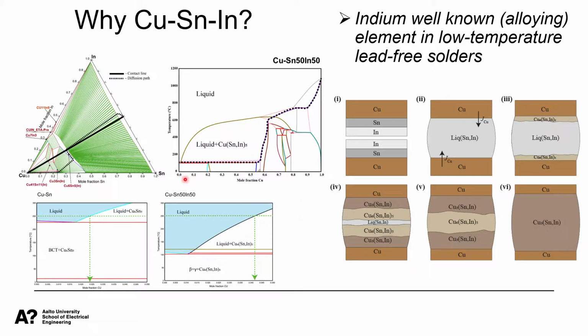In addition, we see that the stabilizing effect of indium to the liquid phase increases the process window in the ternary system, indicated with the blue color here, in comparison to the more commonly used binary copper-tin system. Moreover, we can also see that when the liquid phase is completely consumed by the chemical reactions during the bonding, the remelting temperature of the interconnection should increase up to 600 degrees centigrade. Therefore, we expect that the bonding should be possible at the temperatures around 200 degrees centigrade, but still we should achieve interconnections which are thermally stable up to 600 degrees centigrade.